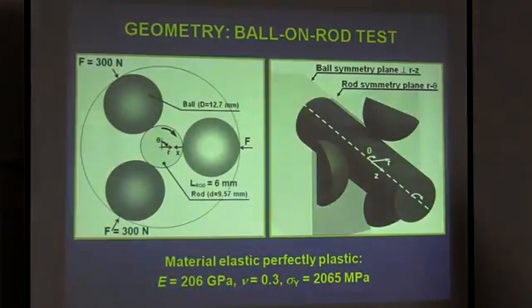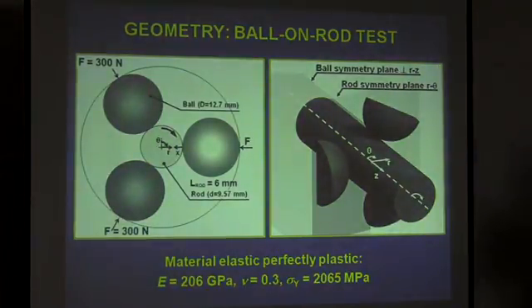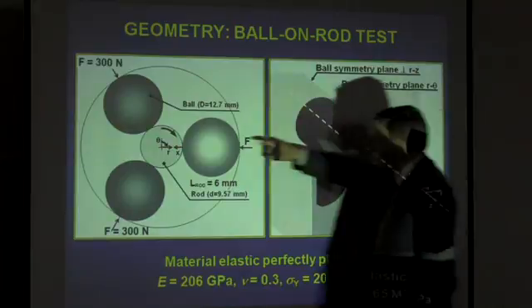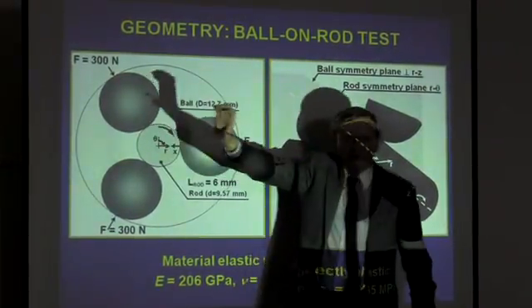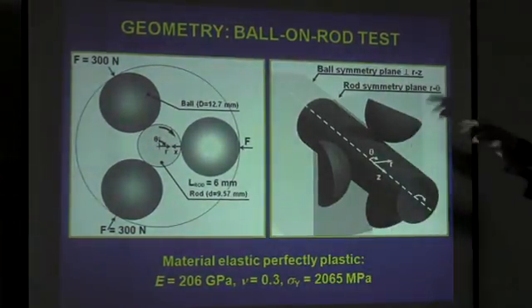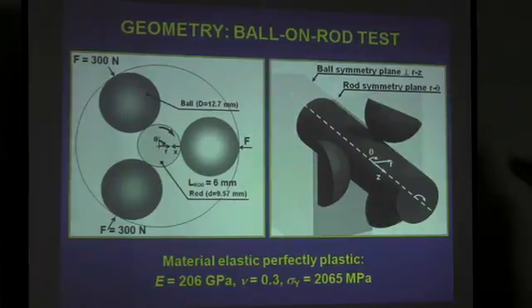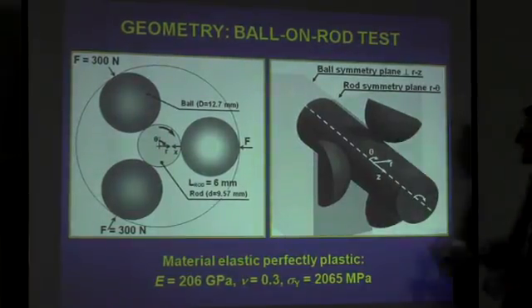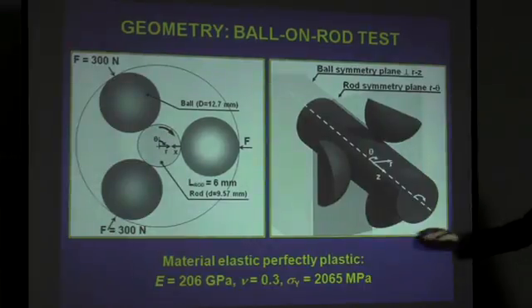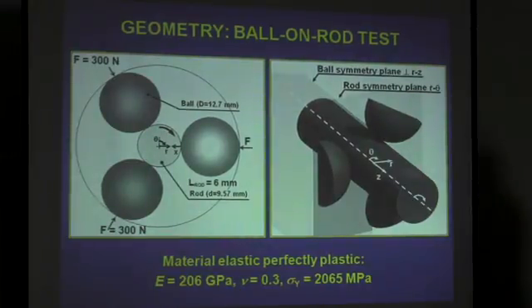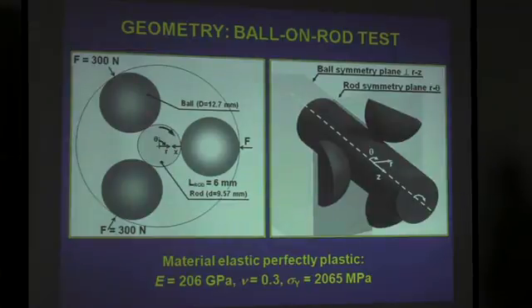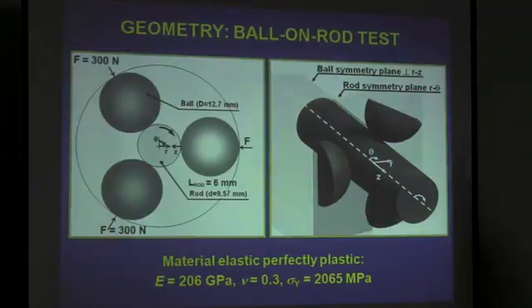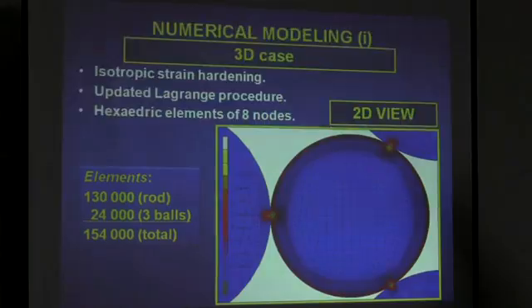Let's go to the problem statement. This is the so-called ball-on-rod test. Three balls rolling over the rod. This is the rod, a cylinder, and these are three spheres, three balls, and the dimensions are here. This is the three-dimensional problem with the planes of symmetry. We assume the material is elastic, perfectly plastic, and this is a typical Young's modulus, Poisson coefficient, and yield strength, very, very high yield strength, high-strength material for bearings.